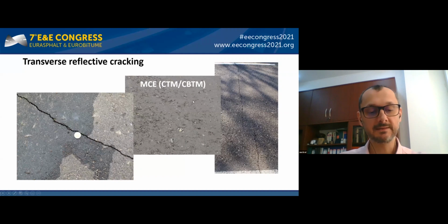Here you can see the effect of used technology on the site. In the middle, you can see the fresh laid mixture looks like a CTM layer without bituminous material. The effect of such over-stiffening of the sub-base often resulted in transverse reflective cracking of the upper asphaltic layers of the pavement, as you can see on the left and right pictures.